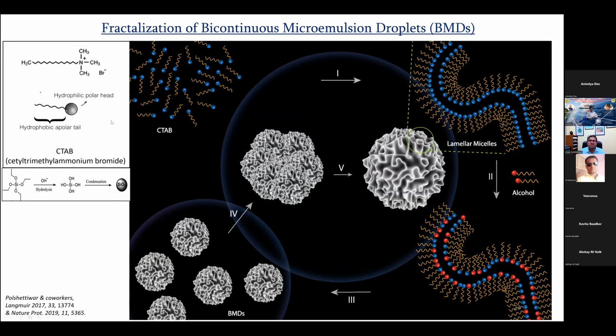What we do is we create a template, and within the template we grow these nanoparticles. So how do we create the template? We use simple organic molecules, for example in this case it's CTAB, cetyl trimethyl ammonium bromide. This has a quaternary nitrogen group, a polar group. The blue ball represents that polar quaternary nitrogen. Then you have CH2, this long hydrocarbon chain up to 16 carbons, which is non-polar. So you have a polar head and a non-polar tail, shown here as a blue ball and a zigzag line.